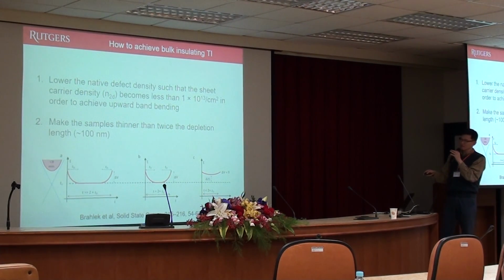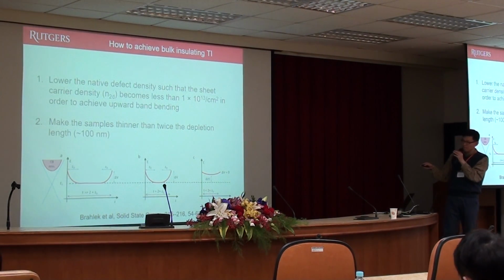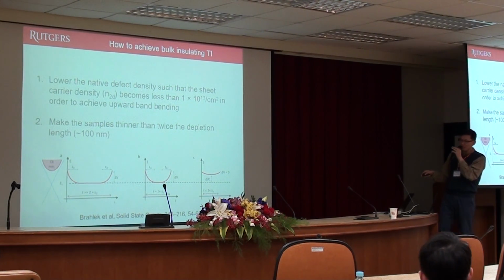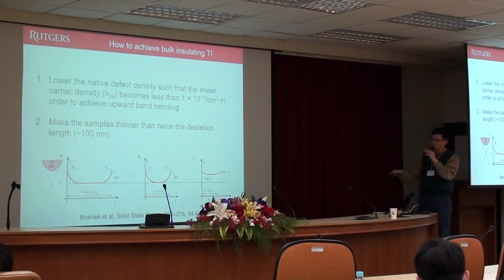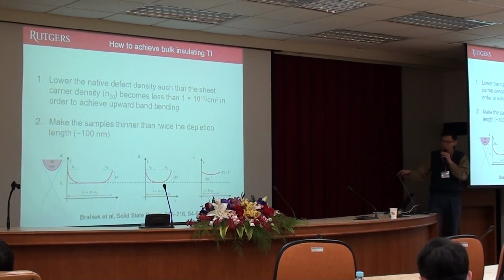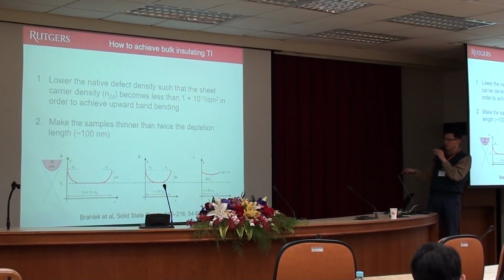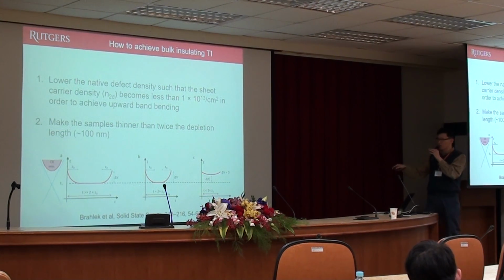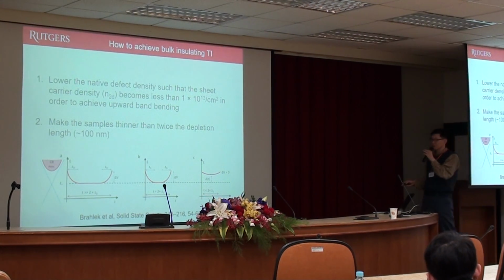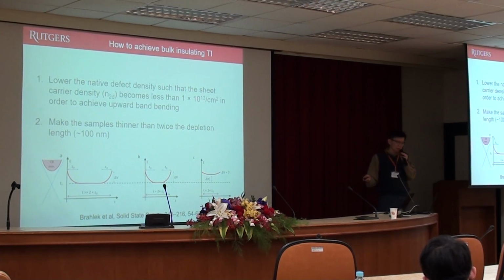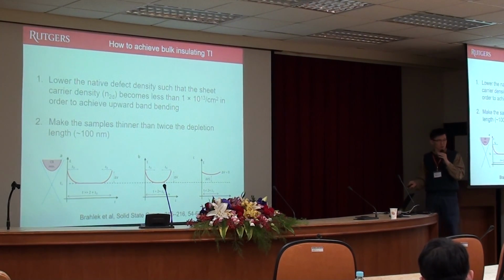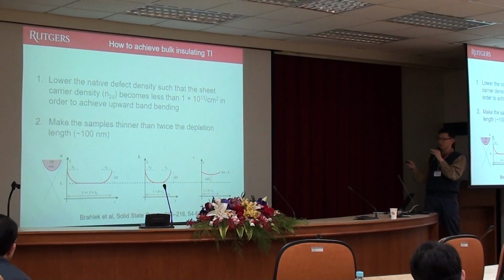So when the film is thick, yes, you have a depletion layer. So basically, you have to first achieve carrier density lower than 10 to 13. Then, if your film is thick, it is still metallic because your bulk is still metallic. The bulk, you can never beat the criteria. So bulk is always metallic if the sample is thick. But if you make it thin, then at a certain point the Fermi level can no longer be above the conduction band. So bulk becomes insulating if you make your film thin. So basically, if you make a low carrier density sample somehow, and if you make it thin, then bulk will be automatically insulating. There could be more complication, but at least at the simplest level, this can happen.